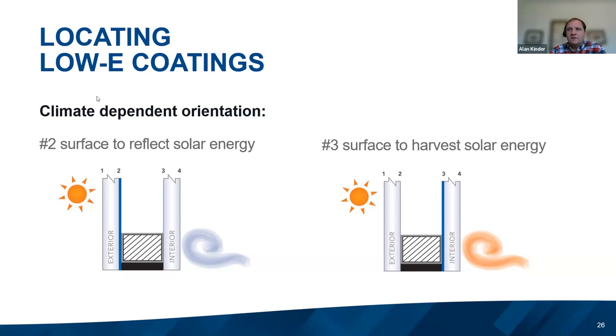The reason being, we talked in the previous slide that they're designed to reflect heat back towards the exterior. Most of these low E coatings do contain silver, and silver can corrode or oxidize over time. So we want to capture it inside of that glazing unit. We then edge delete and we hermetically seal that IGU so that the low E coating is protected. So this gives us our first layer of defense to reflect heat back towards the exterior while still protecting that low E coating for the duration of the insulating glazing unit lifetime.